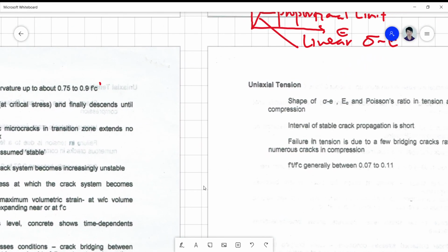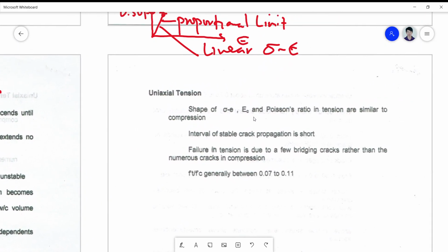Okay, sustained stress conditions mean that your loads are permanently present in that situation. For the uniaxial tension, the shape of the stress-strain relationship is similar, but of course in the other direction. And the interval of stable crack propagation is shorter; it is abrupt and sudden. So you have a brittle failure in case of uniaxial tension. The failure in tension is due to a few bridging cracks rather than the numerous cracks in compression. Normally it's only about 7 to 11% of f'c. So the f compression and f tension relationship is only good for about 7 to 11%.